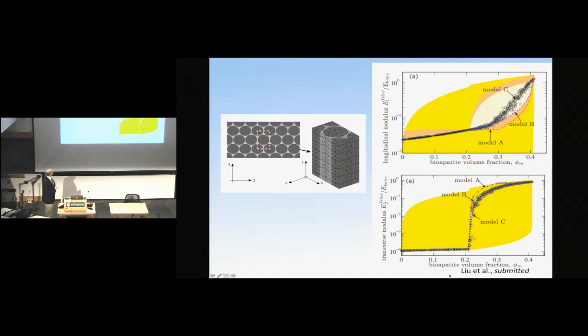Now, an interesting feature of this is that stiffening in the transverse direction, so this is stiffening along the axial direction on this top plot, stiffening in the transverse direction has an earlier percolation threshold for most of these models than the stiffening in the axial direction. So what this means is that, as we saw in that very simple linear elastic optimization, the stiffness in the transverse direction rises earlier than the stiffness in the longitudinal direction.